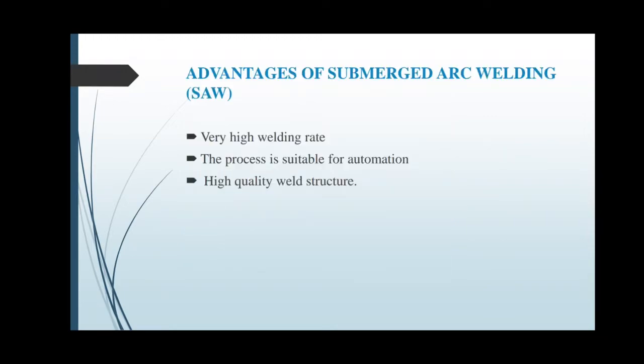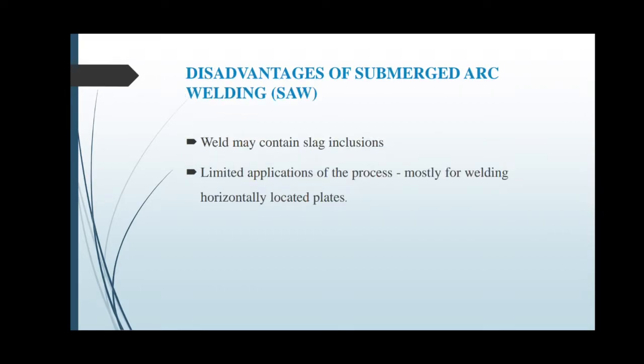Now let's see the advantages of submerged arc welding. It's a very high welding rate process. The process is suitable for automation. High quality weld structures can be obtained from submerged arc welding procedures. These are the disadvantages of submerged arc welding. The weld may contain slag inclusion. Slag inclusion is a weld defect, which means entrapment of non-metallic solid materials in weld metal or between weld metal and base metal, which causes low toughness weld. Second disadvantage is limited application of the process, mostly for welding horizontally located plates.